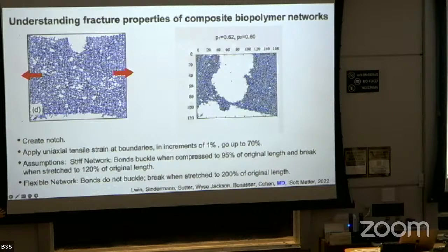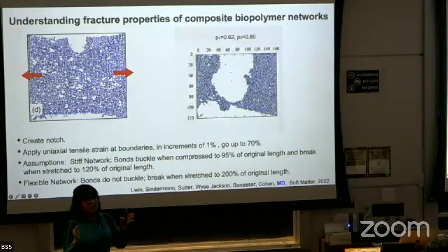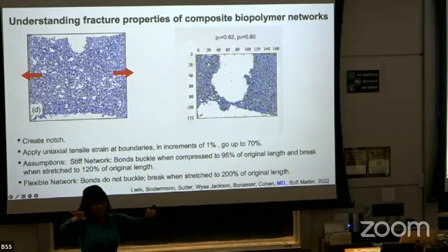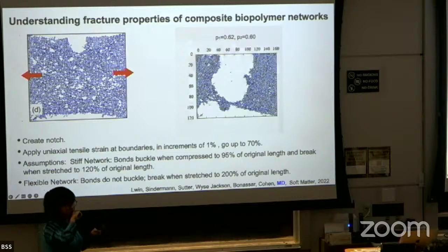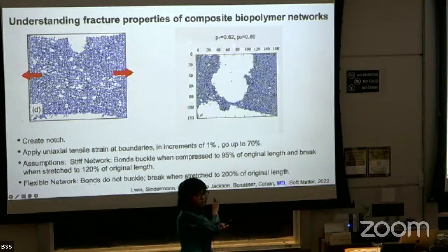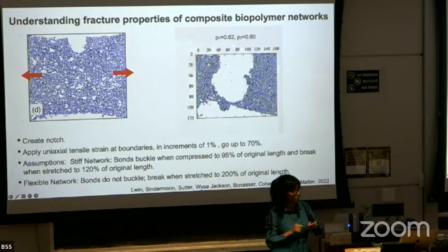For the flexible network, bonds are not going to buckle, but they can break when they have been stretched to more than 200%, or twice their original length. And once again, we remove the bonds once they have crossed this threshold. The other thing that we say is that breaking of bonds is an irreversible change, right? Bonds that are once gone are gone from the network. But for buckled bonds, if you remove the compression, these bonds can come back into circulation. So that's another approximation we are making. So these are all the assumptions that we have now added to this model to look at fracture.